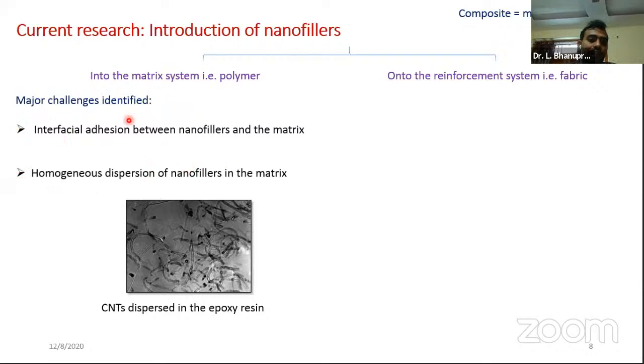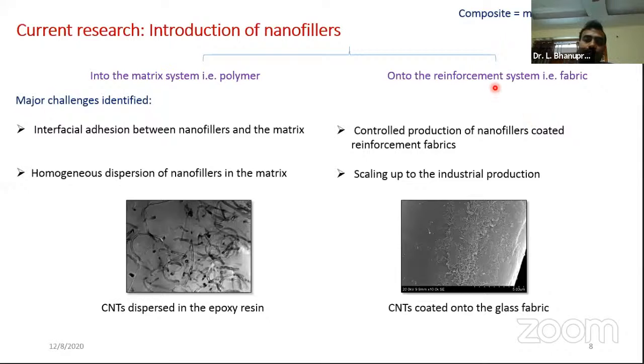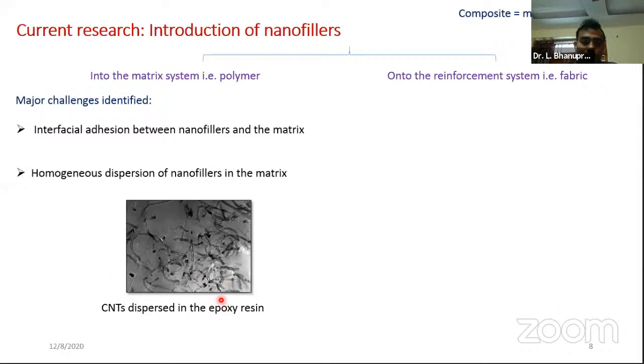So one is the interfacial adhesion, the other is homogeneous dispersion. These two are very critical. These are the challenges when you directly add the nanofillers into the polymer system. Here I can show you an example: these are CNTs, carbon nanotubes, dispersed in the epoxy resin. They are separated from one another. There is no agglomeration here. It is nicely, homogeneously dispersed in the matrix system.